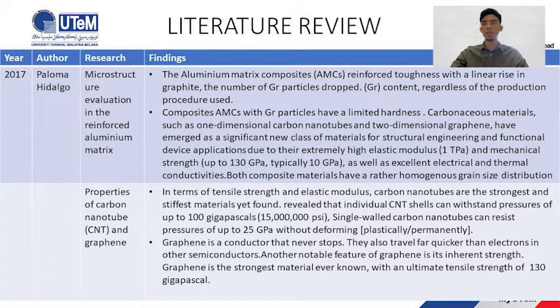The number of graphite particles drops regardless of the production procedure used. And then aluminum matrix composites with graphite particles have limited hardness. And then combination materials such as one-dimensional carbon nanotubes and two-dimensional graphene have emerged as a significant new class of material for structural engineering and functional device applications due to their extremely high elastic modulus, 1 TPa, and mechanical strength up to 130 GPa, typically 10 GPa, as well as high electrical and thermal conductivity.